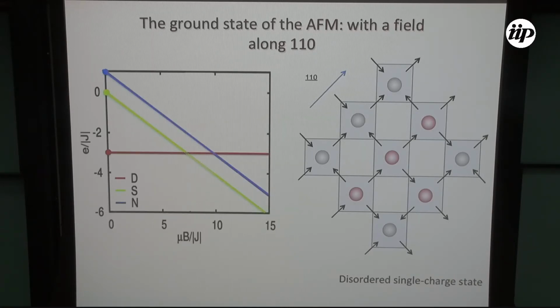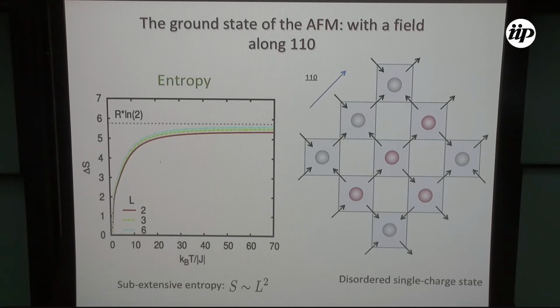Right, so what happens as a function of field? Well, you see that the field does nothing to the energy of the double charges, because this is a perfectly zero magnetic field, zero magnetization state. So the magnetic field does nothing to that, but it lowers the energy of the single charges and of the neutral charges. And what we found interesting was to work within this square, within this range of fields, where now your ground state is of single charges and your excitations are double charges. So your ground state is like this liquid of monopoles, and your excitations would be to make them double charges. So what's the entropy of the system?